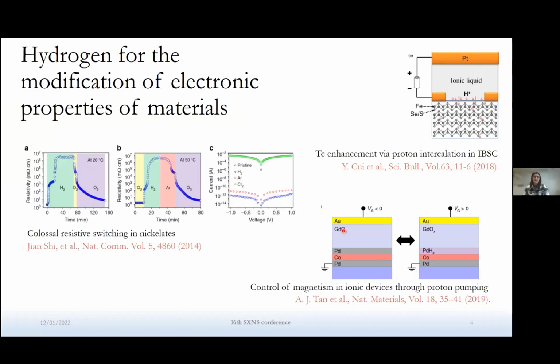Another branch where hydrogen has become more and more important is the field of physics, where hydrogen is used as a dopant to modify electronic properties of a host material. So here are just a few examples, some pretty recent ones. For example, here it has been shown a colossal resistive switch of rare earth nickelates when applying hydrogen atmosphere or oxygen atmosphere. Or in this case, it has been shown that there is a sensitive increase of superconducting temperature in iron-based superconductors via proton intercalation, or as well, hydrogen is used already in ionic devices. For example, in this case, due to its ability to change the magnetic anisotropy of a thin magnetic layer. So in all of these cases, we are interested in knowing how much hydrogen is involved in the process and how much the quantity is related to the change of the electronic property.